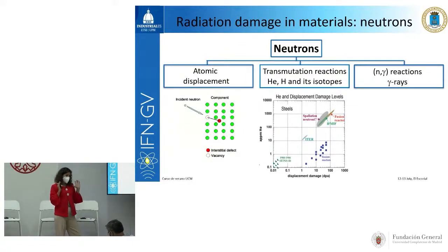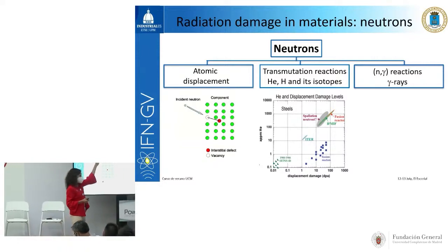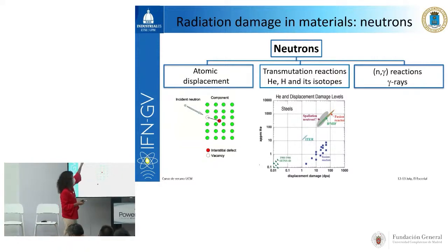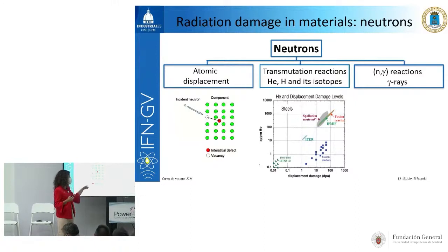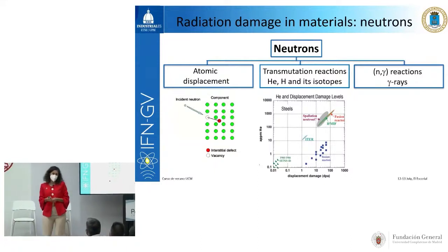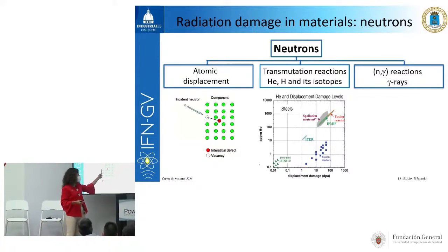Then we need to identify what kind of damage this radiation is going to produce. So basically, neutrons are going to produce atomic displacements, okay? When the neutron energy is above a certain energy threshold, the neutron impinges into the sample, and one lattice atom is displaced, kicked out of its lattice position, and becomes an interstitial, okay? So this creates a pair which is a vacancy and an interstitial. This pair is called a Frenkel pair, okay? So we are going to have vacancy and interstitial Frenkel pairs.